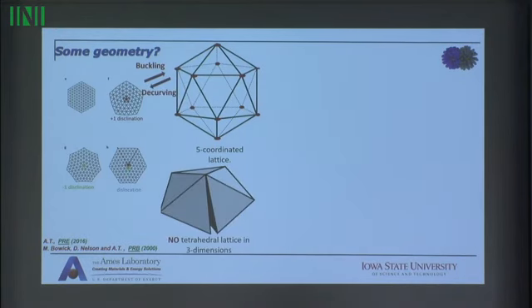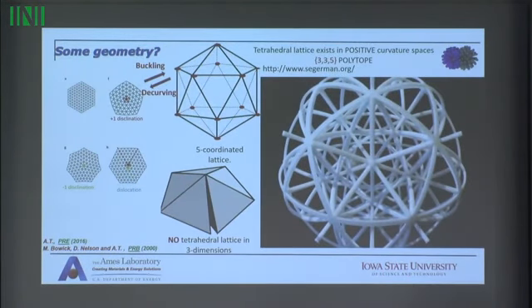If we try to do the same thing in 3 dimensions, we cannot do it because when we start putting tetrahedra, perfect tetrahedra, there is this small gap, and that prevents us from tiling the entire space with tetrahedra. Now, if we go to a 4th dimension, here we have it by my good friend Henry Segerman. This is actually the 335 polytope that is stereographically projected in 3 dimensions. You can check that this is actually made of perfect tetrahedra, that if we were able to live in 4 dimensions, we would see as perfectly equilateral.